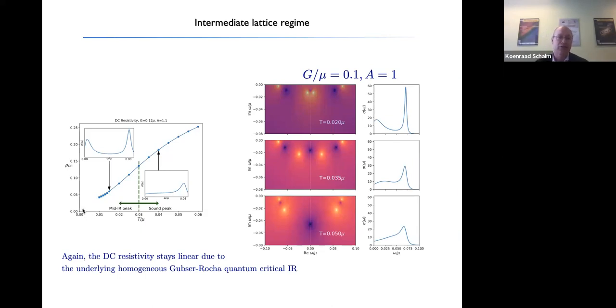So we actually believe that you should have a full linear regime here all the way up to here, where here you have a very Drude-like behavior. Here you transition to the mid-IR peak behavior. And here you have this bad metallic sound mode dominated optical conductivity. Even though throughout, again, the DC resistivity stays essentially linear in the temperature.